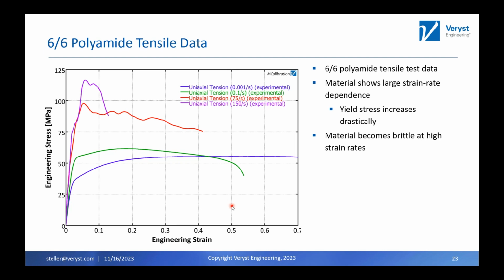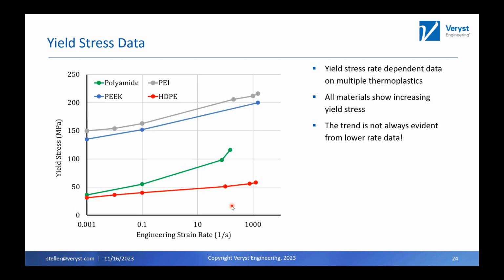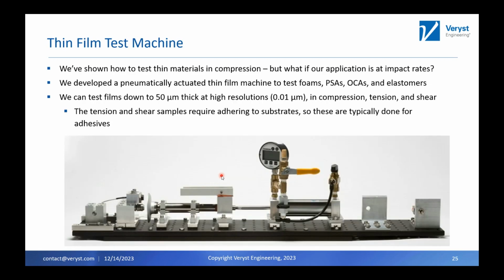So you might be saying, Sean, that's one data set. Here's 4 data sets that we have internally on our own data that shows the yield stress as a function of engineering strain rate. So you can see all of these have an increase. The x-axis is in the log scale, the y-axis is linear. So you can see that you're getting increase in yield, and sometimes you get some unexpected behavior where you see a transition at the higher rates. So that's why we need to test at high rates versus low rates.